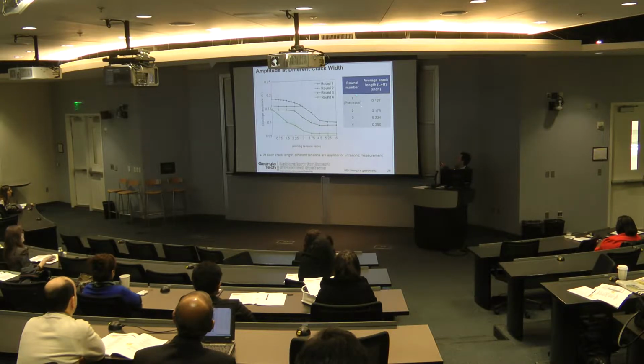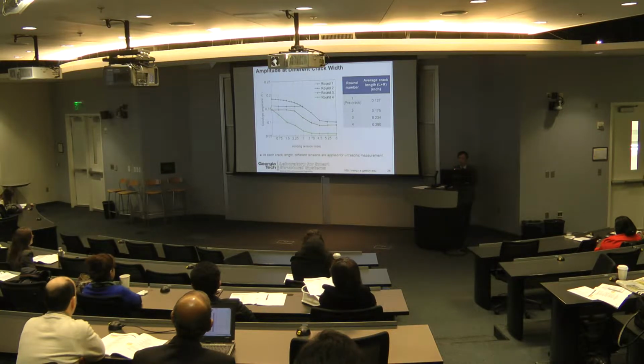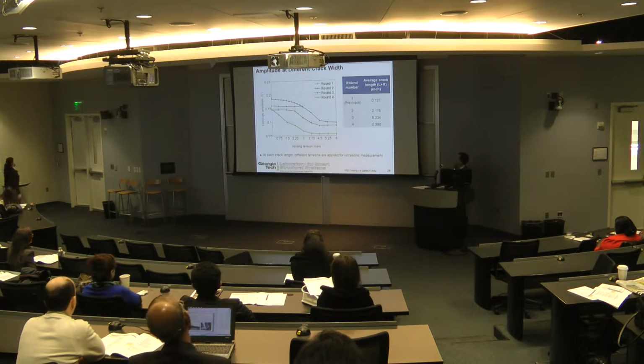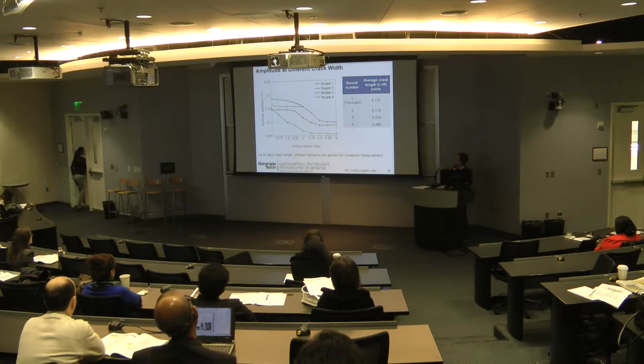So every round here you see is 1,000 cycles of fatigue loading. After the first round, that's the crack length in inches. Second round, third round, fourth round. Then after a few hundred, the specimen just broke apart. So at every round, the black line is the round one.